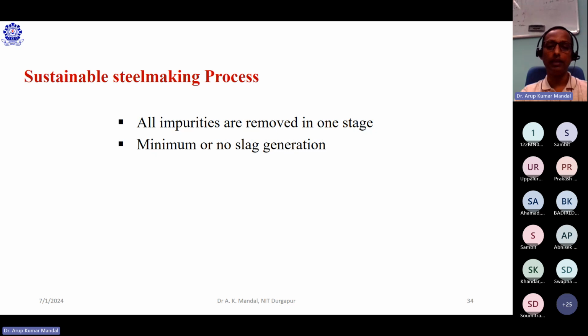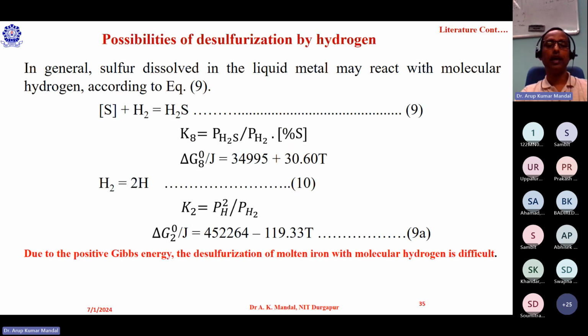So how can we do it? As we discussed, hydrogen can reduce all the impurities at a temperature within the range of steel making. But the problem with hydrogen is, if you see the reaction of hydrogen with the sulfur dissolved in the iron, due to the positive Gibbs free energy, the desulfurization of the molten iron with molecular hydrogen is difficult.